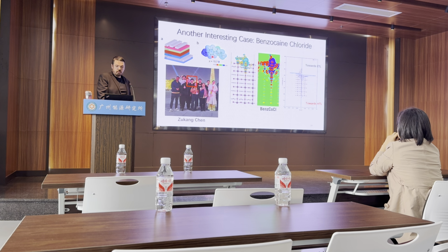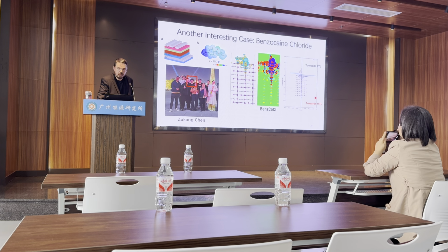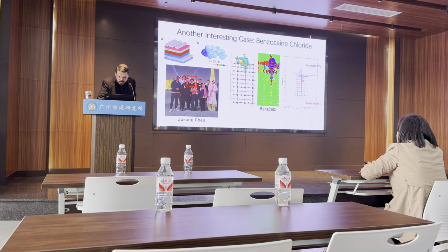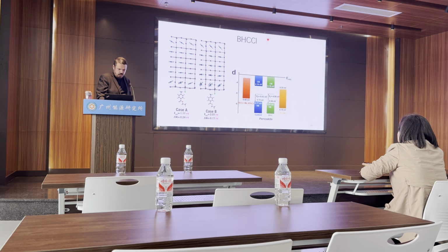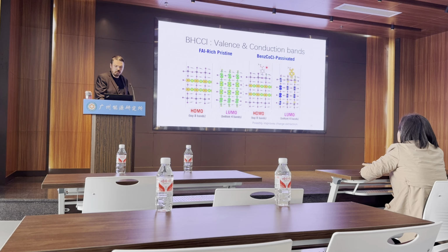Okay, another interesting case is benzocaine chloride, and here we're considering an NIP device, so the polarity of our displacement diagrams changes. Now the ETL is up here and the HTL is down here. Again, the displacement diagrams are similar, and here's the benzocaine. The big thing here is, if you look at various calculations, you can see that the absorption energy in the work function varies quite a bit between various cases. But in general, it's negative, and in experiments also negative, so that checks out. It does agree with experiments.